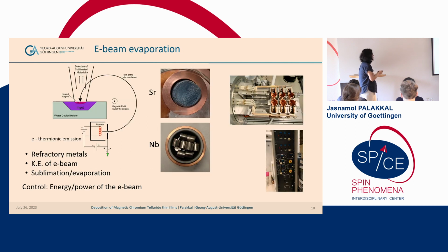And this is how we use electron beam evaporation pockets. So in my former group, we had 6 electron beam pockets. We can simultaneously evaporate them. And we take the elemental sources in their solid form like this. So depending upon the material, you have to take them in different ways. So this was strontium, this is niobium. Niobium is a refractory element, and if you want to use niobium in an MBE, you cannot use just an effusion cell. You always have to go for an electron beam evaporation.